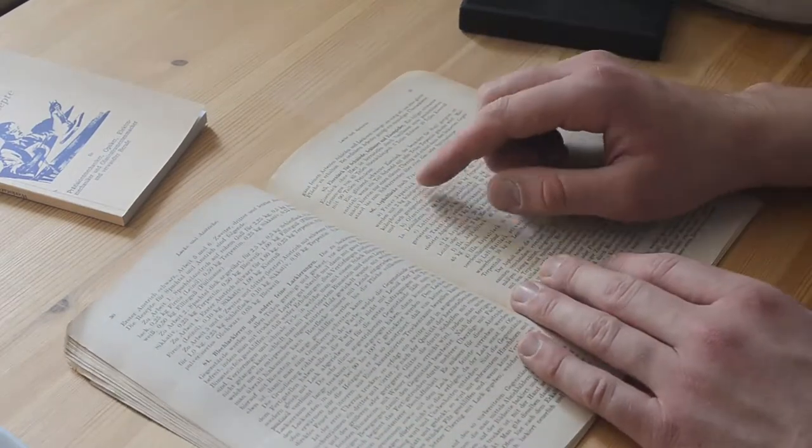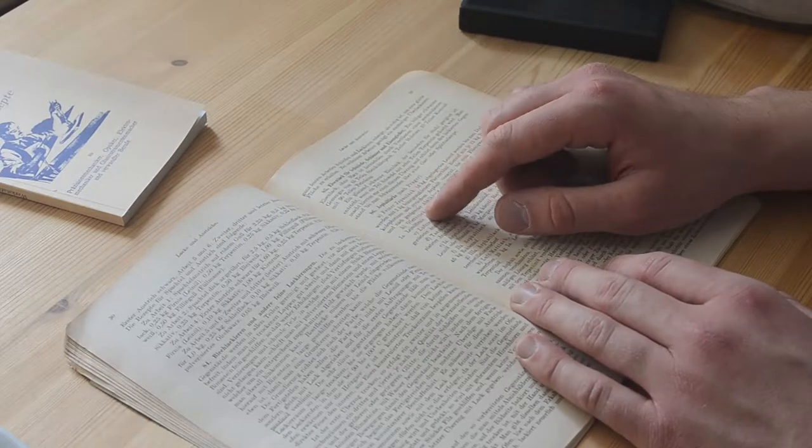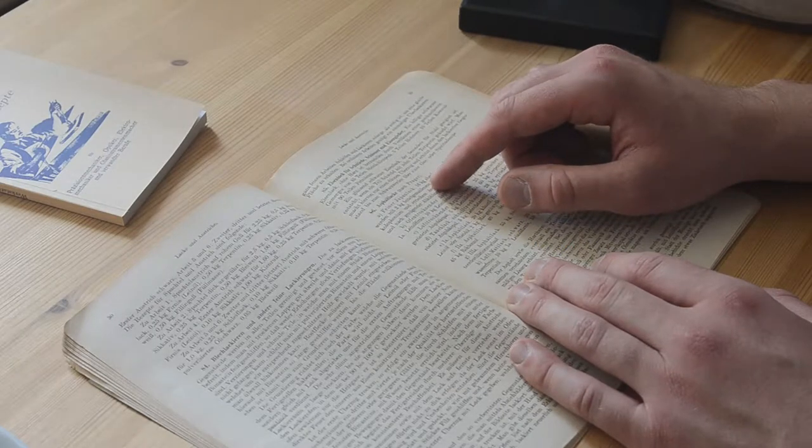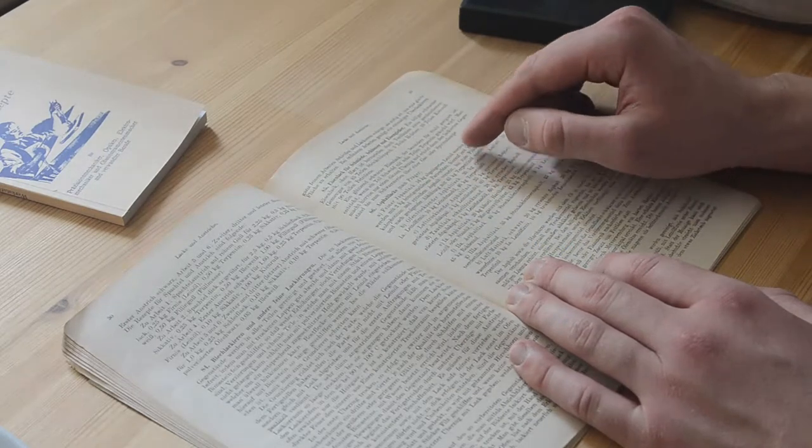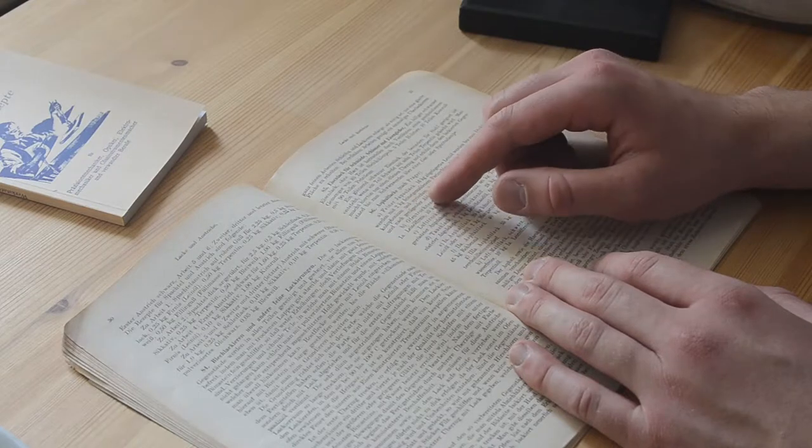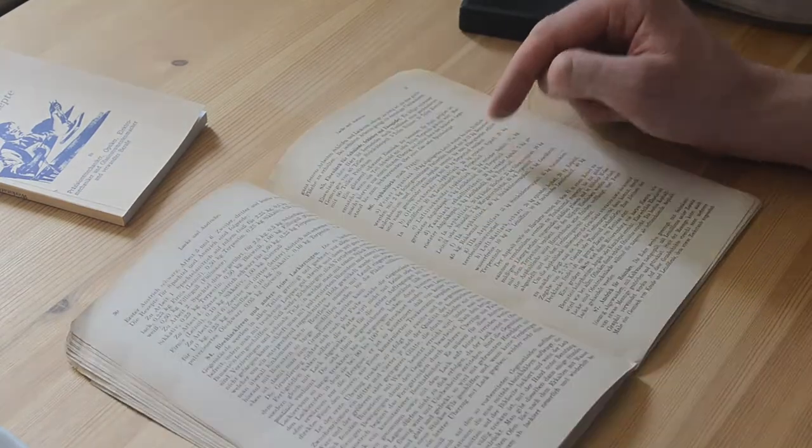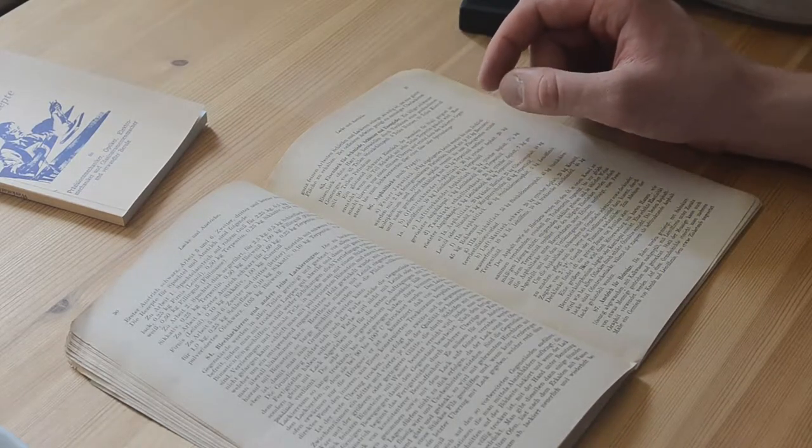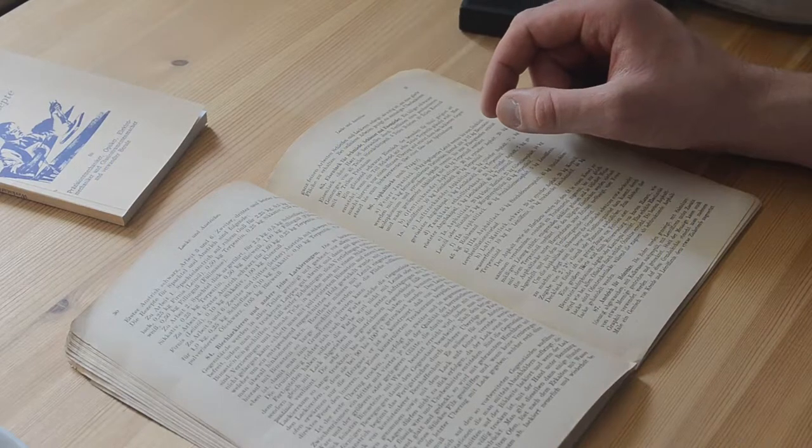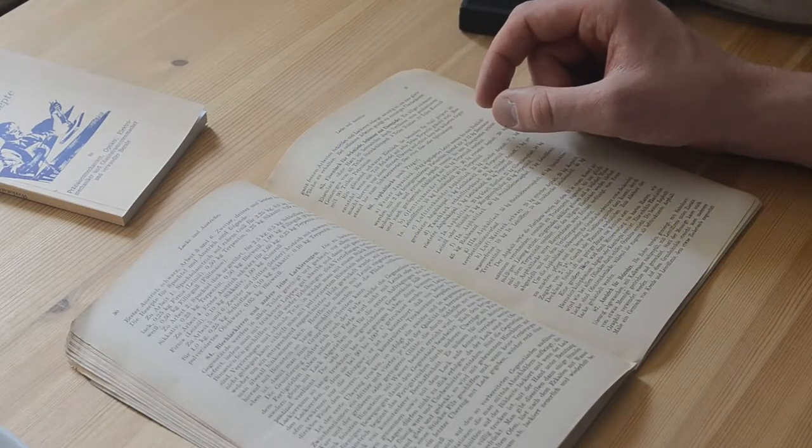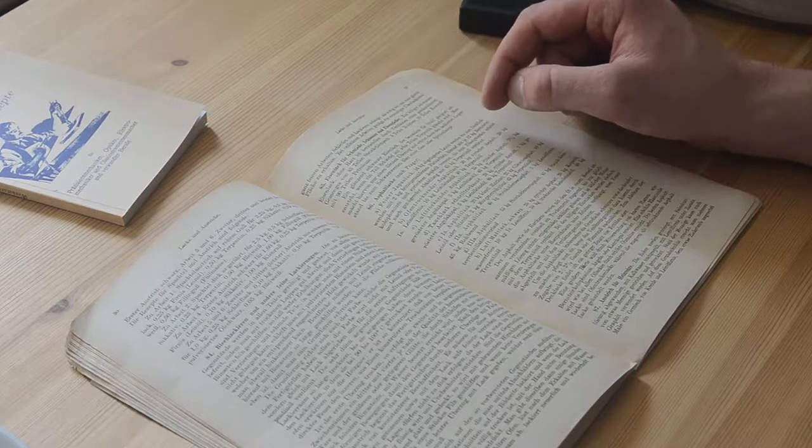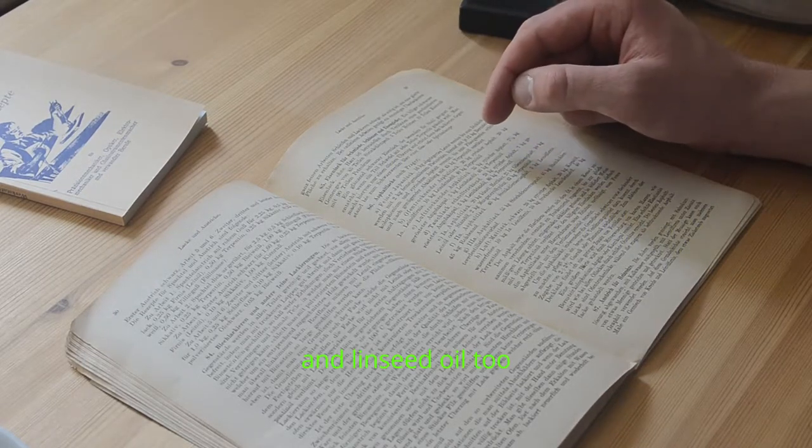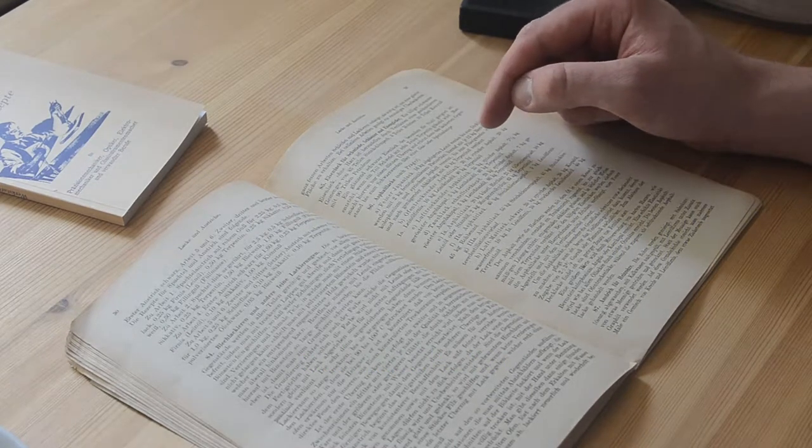Here's the recipe for very fine Japaning: 16 kilogram linseed oil, 2 kilogram Paris blue pigments, 12 kilogram colophonium and asphaltum. This is both combined because first you would melt colophonium and asphaltum in one bowl till it's like Nutella, and then you put all the other ingredients into that liquid.